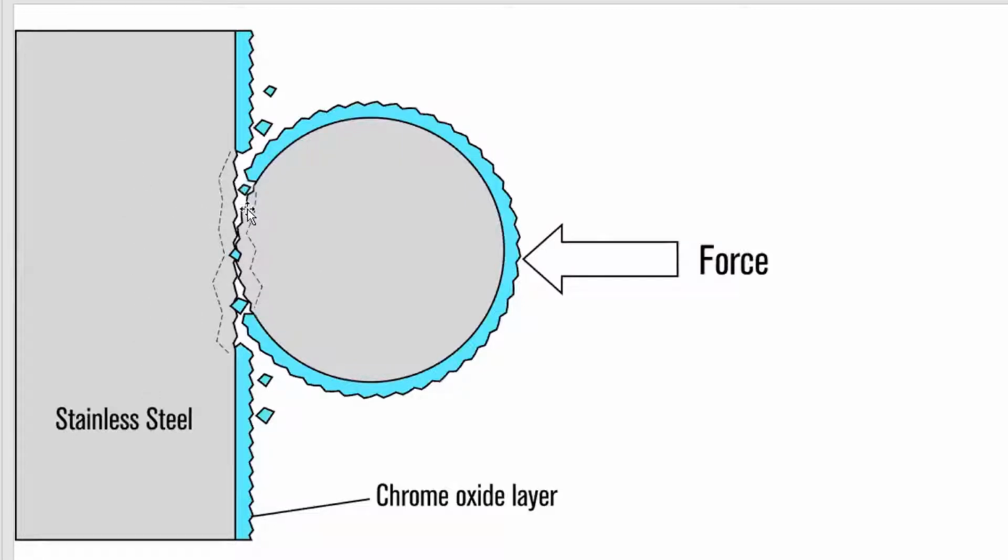what it can do is this O-ring, a little bit different than this O-ring, will actually conform itself slightly to this substrate. But what happens is this O-ring is actually flexing back and forth, kind of like kneading bread dough. But since it conforms to this, guess what it does? Not only is it creating some slight adhesive forces in here, but it's also sealing off any sort of oxygen that might remain in there.